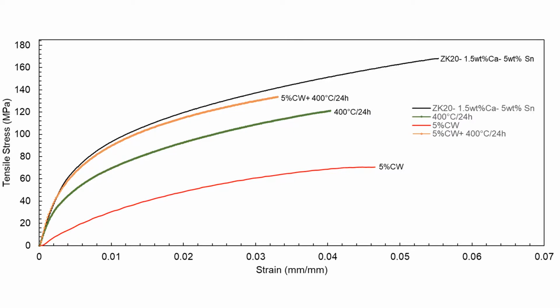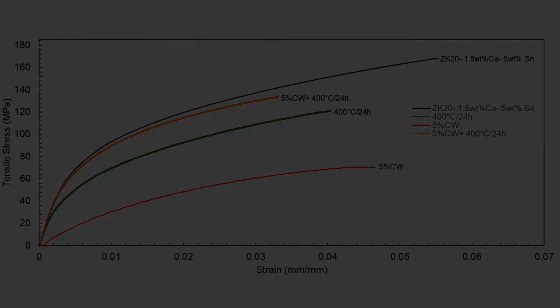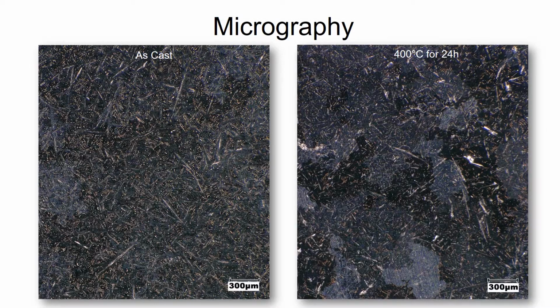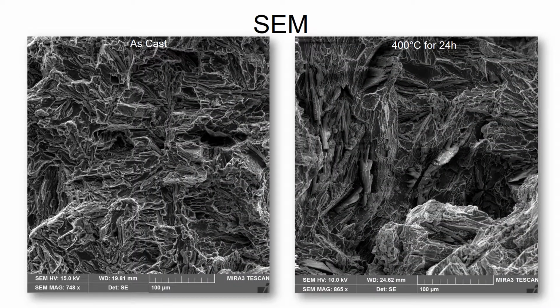In the case of the alloy with 1.5 weight percent calcium and 5 weight percent tin, the as-cast sample produced the highest values of elongation, Young's modulus, yield strength, and ultimate tensile strength. These properties are most likely due to the formation of the magnesium, calcium, and tin phase that occurred in this alloy in greater amounts when compared to the other ones. In the micrography photos, we can see how the heat treatment slightly reduced the presence of this interface. On the SEM photos, the feather-like magnesium, calcium, and tin phase can be appreciated.